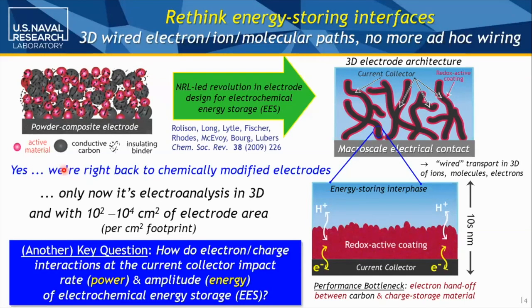But we still have some key questions where a lot of work needs to be done. And our group can dip into this periodically. We have to sell programs and sometimes they can't look too applied. But we are talking to carbon for the most case in a practical battery world. And carbon is not the best electron transfer interface in terms of your heterogeneous electron transfer rate constant. But we're living with carbon because it's cheap and we can do a lot of fun things with it. So if you're worried about energy and power, ultimately you have to think about what is my heterogeneous electron handoff between the active material and the carbon. And we're still not doing that particularly well because we're working with carbon. So I'll leave that as an open question.